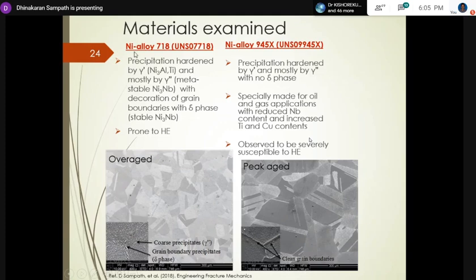As I told, nickel alloy 718 is a precipitation hardened alloy. It has gamma prime, which is a combination of Ni3Al or Ni3Ti. And the major strengthening comes from gamma double prime, which is Ni3Nb, niobium, in the matrix. Here I am showing the scanning electron microscope image. Here I'm calling this overaged.